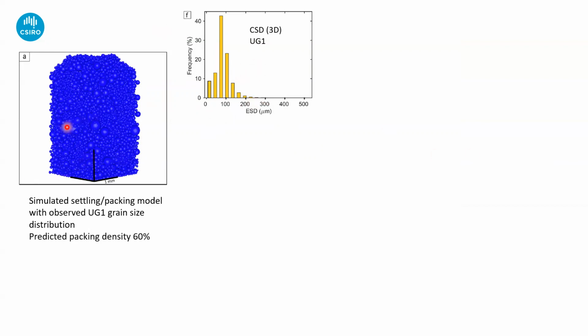And then what we've done is to compare that with a computational simulation, which basically takes a population of grains with that exact grain size distribution and generates a gravitational pack. So basically just dropping them in a bucket and looking at the characteristics of the grain pack that you generate. There are various different ways you can do that, but this is the one that we came up with. A number of parameters come out. One of them is the packing density. For this particular grain size distribution, the predicted packing density is about 60%. In other words, you'd expect a rock which is 60% crystals.